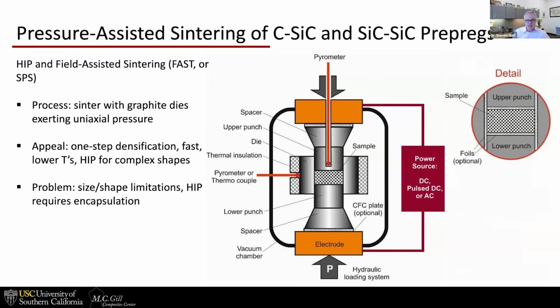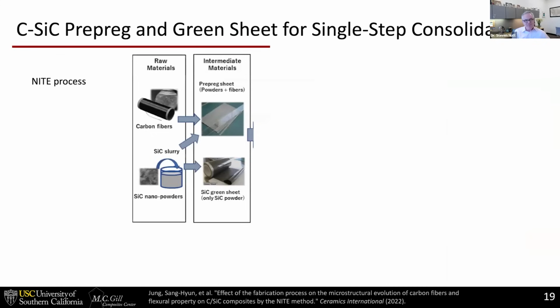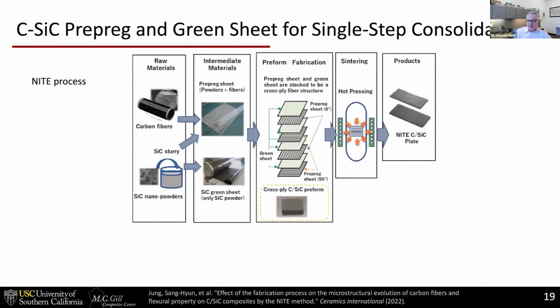In any press operation, there's going to be size and shape limitations. This is an interesting variant developed by a Japanese company called NITE, for nano-infiltration, nanoparticle infiltration and transient eutectic. I'm not going to try and explain all that, but basically it's infiltration of a slurry into fibers, just like the previous slide, but different constituents here, not Ox. Now we're talking about silicon carbide nanopowders. And then layering up the plies, just like you would with prepreg, and hot pressing, to form either carbon-SiC or SiC plates.